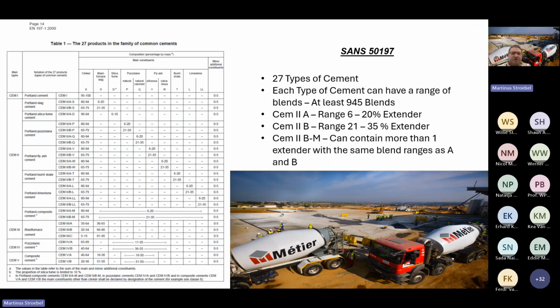When you then look at the cements that we are able to use, there are 27 families that we can, as a ready-mix supplier, make use of to supply concrete. And remember, every component in that cement or cement blend comes at a cost. It depends where in the country you are. If you're close to a slag source, slag might be cheaper, fly ash might be cheaper. If you're closer to a cement factory, that also plays a role in the transport. So there are 27 types of cement that you can start off with to blend.